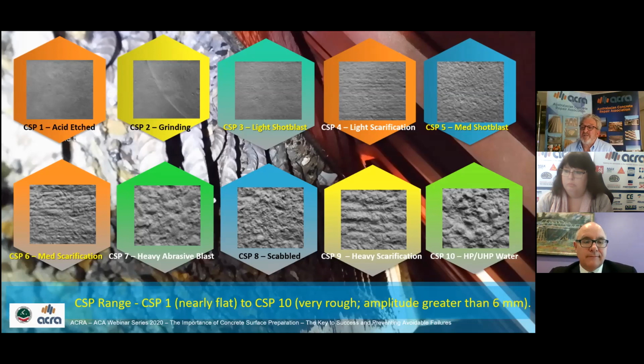Each carries a number ranging from CSP1, which is nearly flat on the top left-hand corner there. That's acid etched, while we don't do that too often these days, through to CSP10, which is very rough, and a profile of over 6 mm. These profiles, the replicas were made through a variety of preparation methods, as we can see there. And what we've done is represented the profile height that's required for the different products.